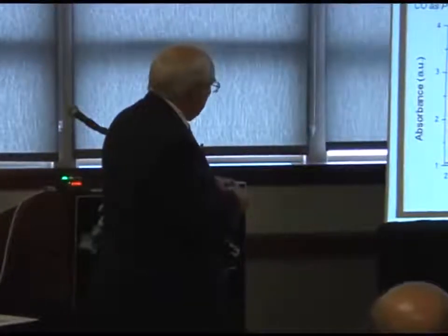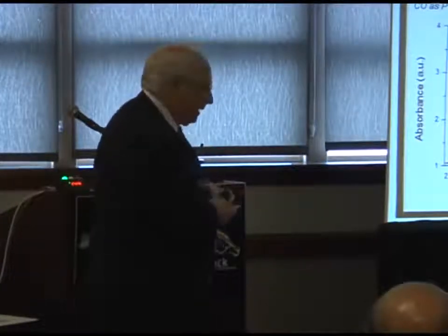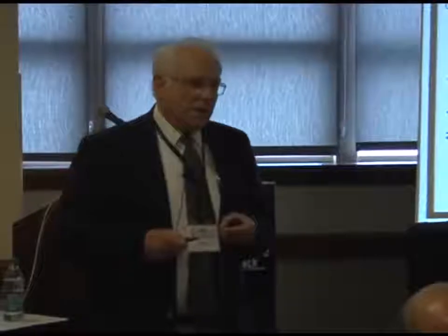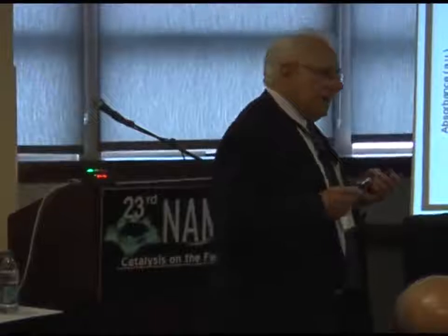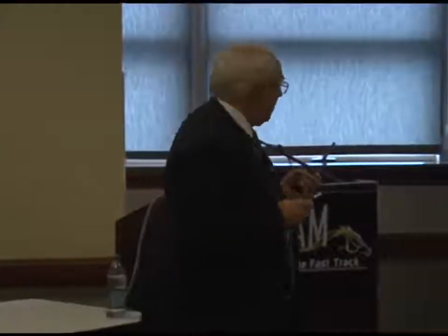The other thing, please notice here, is that the zeolite supported sample is characterized by very sharp carbonyl spectra, consistent with the high degree of uniformity of the sample. In other words, almost all the environments that the iridium dicarbonyl sees are essentially identical.